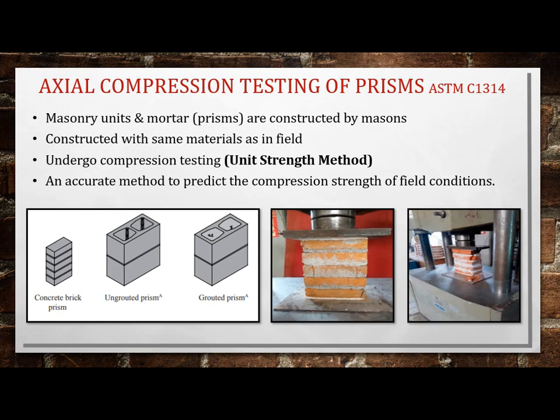The third way, and what I feel is the most accurate way to predict the compressive strength of field conditions, is to create a prism. These are made by masons using the same materials as in the field. So you use the same block, same mortar, some grout. You would actually make a prism, a stacked test sample. You leave it in the field. These can be made in the laboratory also. They stay undisturbed for 48 hours. You cure them for 7 or 28 days, and you do a compression test. And so that's called the unit strength method. This, in conjunction with specifications by proportion, is what I feel is the most accurate way to have a good grip on the compressive strength of field conditions.